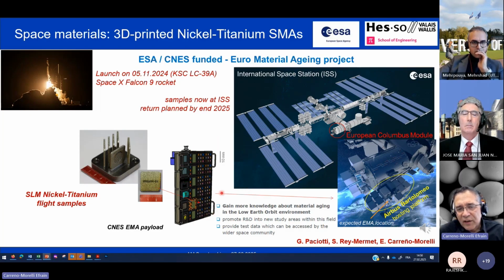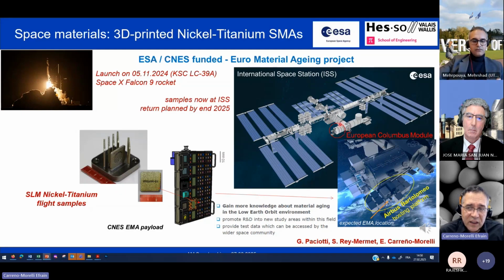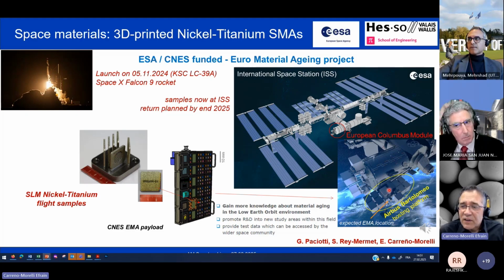Then this is a sample holder, and here there are specimens from several European labs, from 2 Swiss labs in particular, and we have some of these nickel titanium plates. There is one with shape memory properties, the other with superelastic properties, and after 1 year in space, the specimens will be recovered, and we will test if the properties have changed. This is done near the Columbus module, and especially in the Bartolomeo hosting platform, which is outside of the International Space Station. The launch was last year in November, and we expect to recover the parts by the end of 2025.